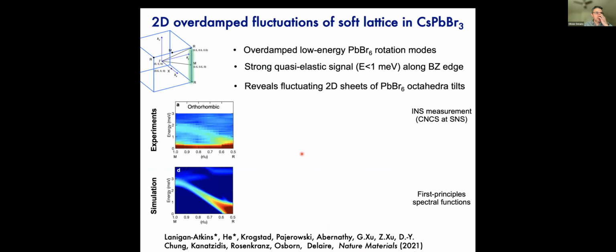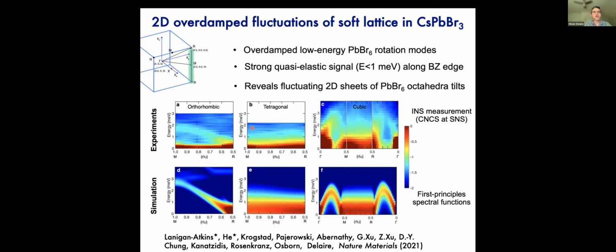So we've done neutron scattering and inelastic X-ray scattering on the double perovskite that I'll show next. But the neutron scattering was done first on this compound here, and it allowed us to see that when we focus on the edges of the cubic Brillouin zone, we find that there's a completely overdamped phonon branch that is derived from the zone boundary acoustic phonon modes in the structure. But if you look away from the zone boundary, you'll find that there are still sharp acoustic phonons.